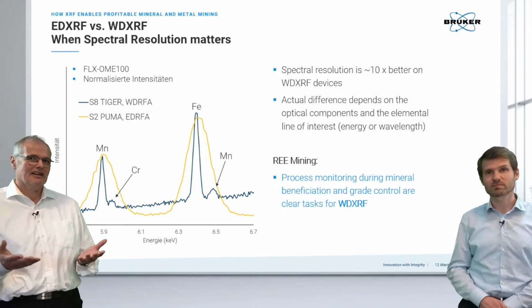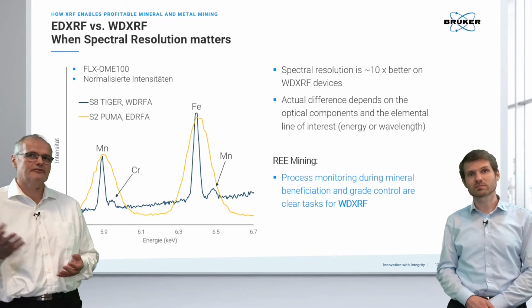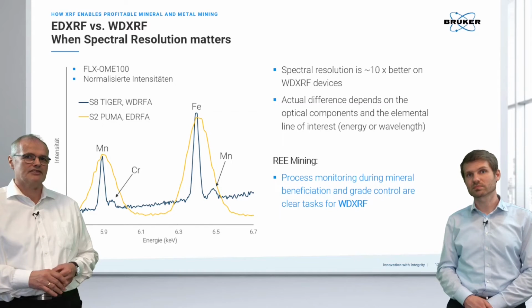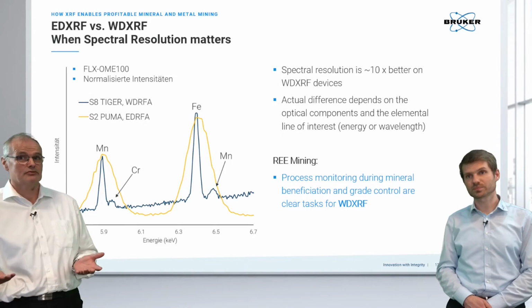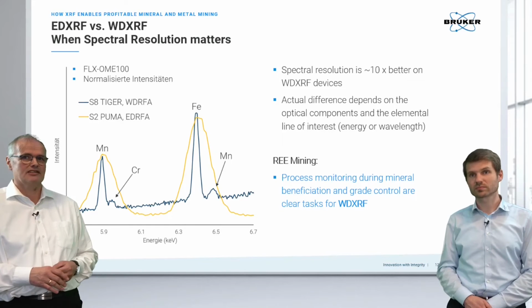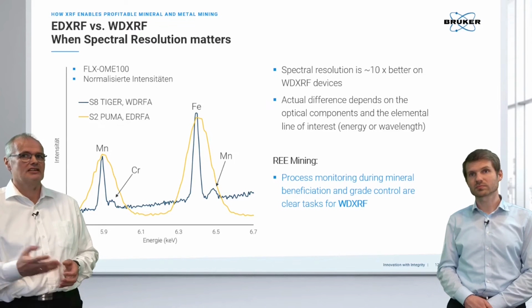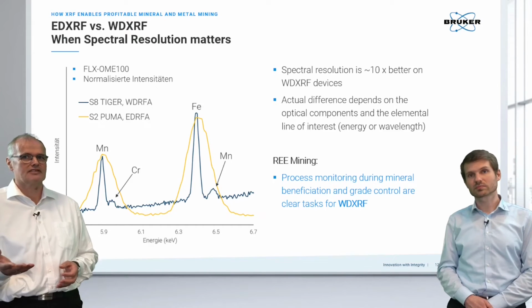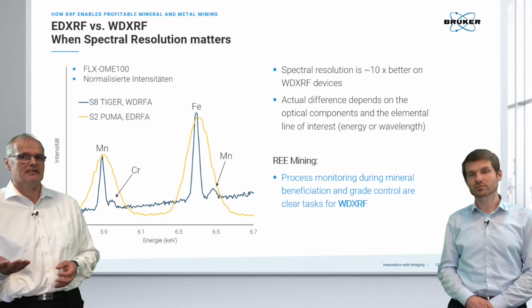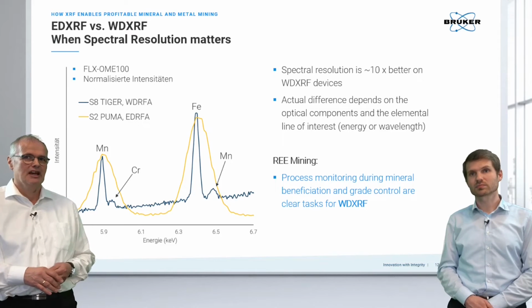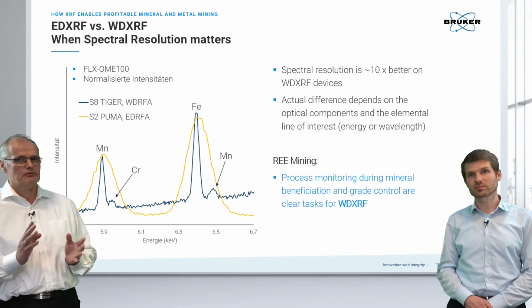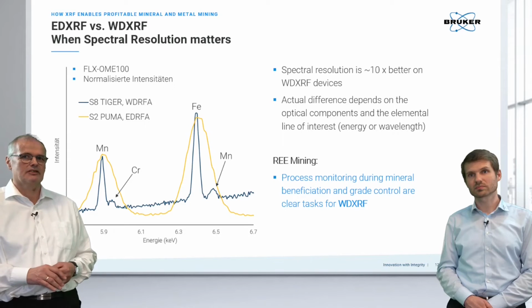Yeah, I mean, so the big difference here is actually the wavelength dispersive provides a better spectral resolution. And we can see this example here where we see the iron peak. The yellow curve is the ED spectrum. The black is the wavelength dispersive spectrum. And this is a very critical difference between the two technologies.